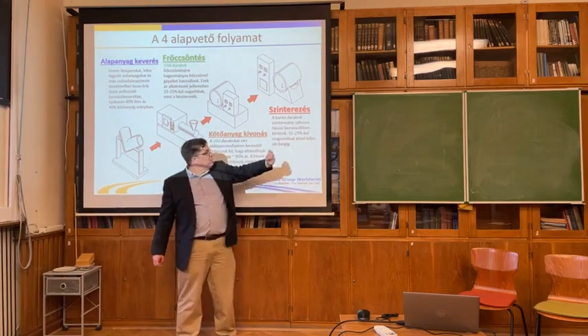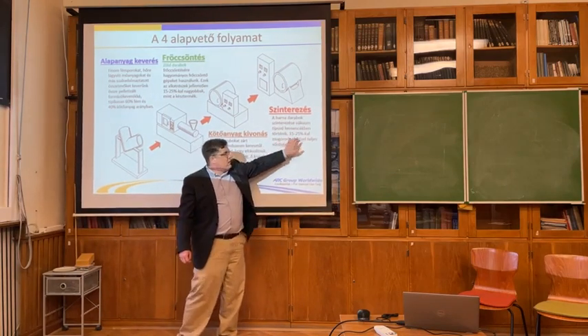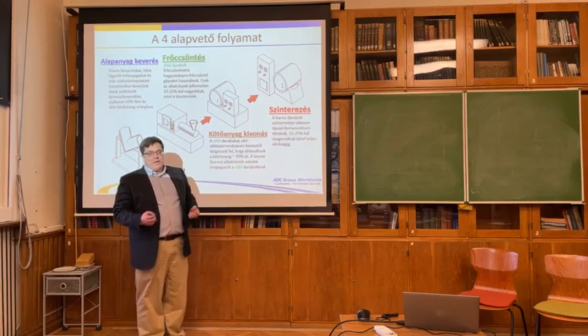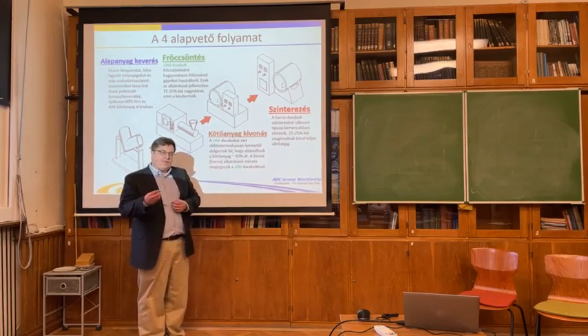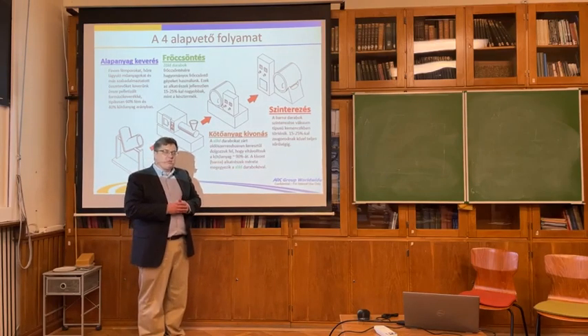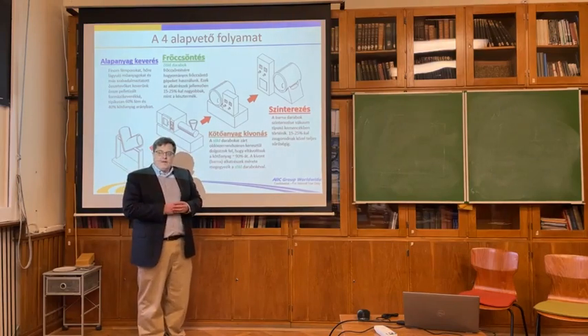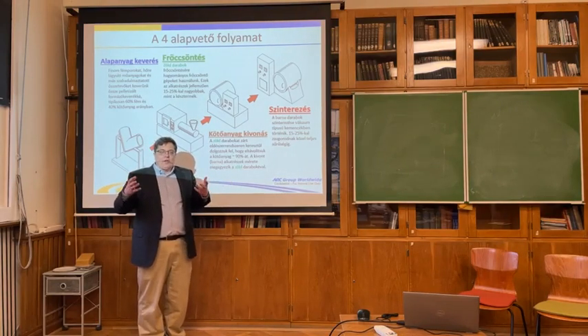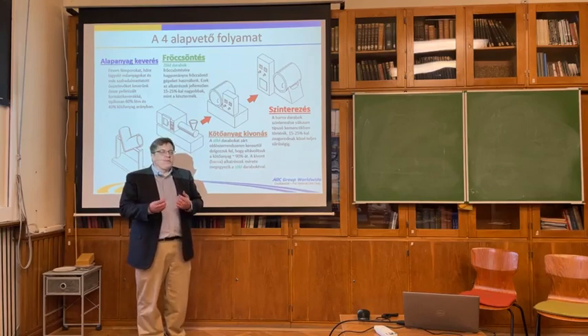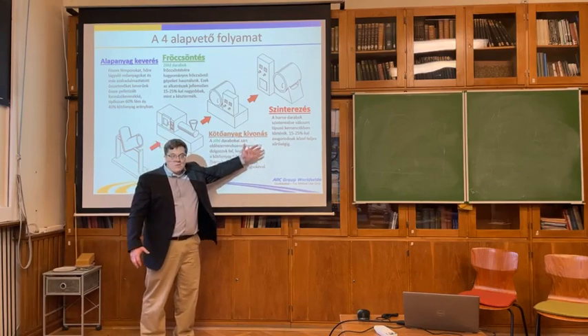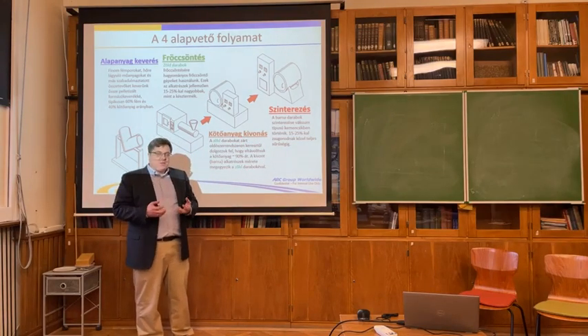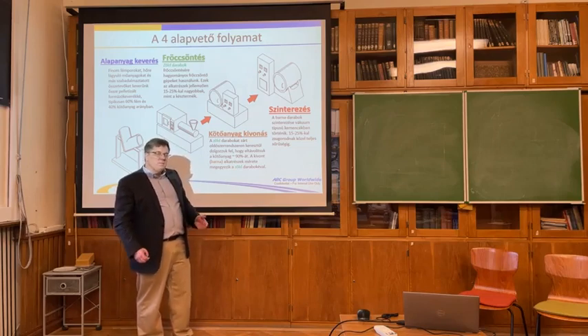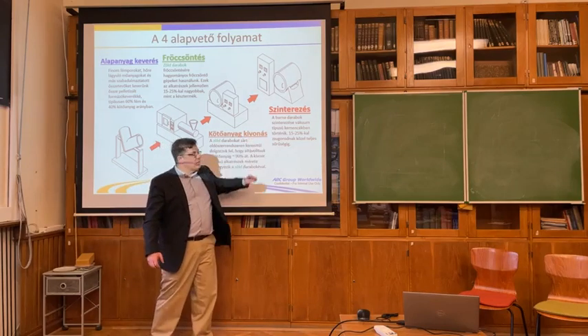And I can show you that. So we usually get between 15 to 25% shrink. And when we show people in the plastics or the powder metal industry, they're like, wow, that's a lot of shrink. They're used to 2 or 3% shrink, not 20% shrink. So that's actually a big value for shrink when you put it through the sintering process.